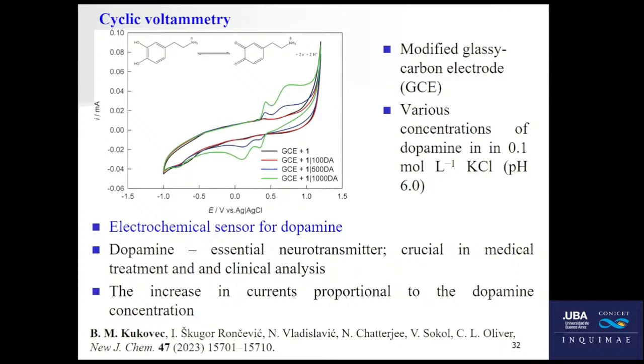Again, we used cyclic voltammetry to see if we can use this compound for some analytical purpose, and this time we were lucky. Before I explain why, in this case we used a modified glassy carbon electrode, again mixed with the cobalt polymer which I explained, and this time we tested it with dopamine. Why dopamine? The structure of dopamine is shown here. It's not a complex molecule, that's what I wanted to say. It's an essential neurotransmitter, crucial in medical treatment and clinical analysis, and regardless of the many analytical methods to determine dopamine in biological samples, there is a demand for more and more precise methods for quantitative determination of dopamine. So that's why dopamine.